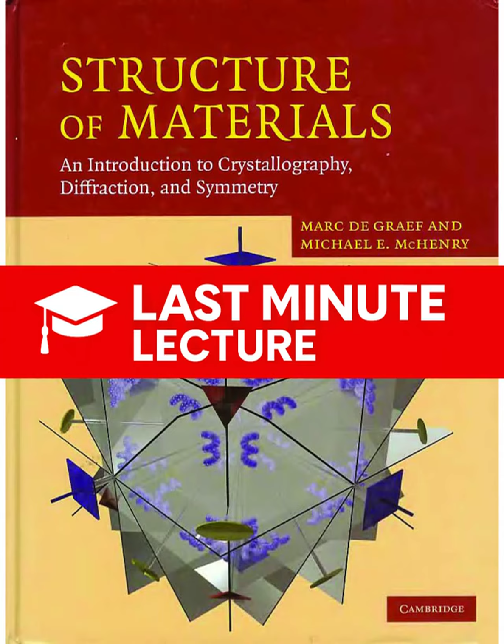We are now transitioning into the one-dimensional linkages, where the tetrahedra finally start touching. We begin with pyrosilicates, or sorosilicates. Pyrosilicates, also called disilicates, are defined by having isolated pairs of SiO4 tetrahedra that share exactly one vertex. One vertex. Just one. This results in the characteristic Si2O7 structural unit. If you break that one vertex, you get an orthosilicate. If you share two, you start forming a chain. This is the structural middle ground.